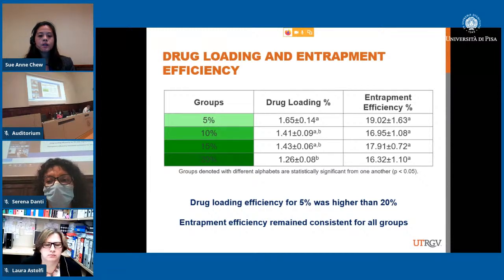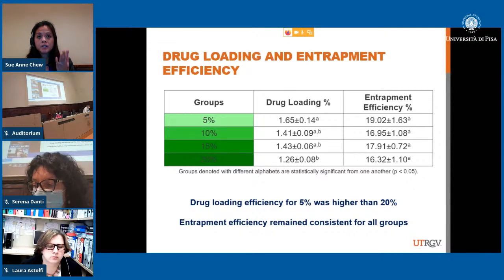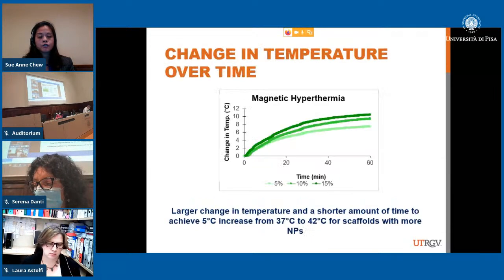So, we wanted to characterize them with drug loading and entrapment efficiency. We were able to make sure that the scaffolds were generated evenly and repeatably, where their entrapment efficiency remained consistent for all groups. But as expected, if we put more nanoparticles into the scaffolds, the drug loading percent goes down because the iron oxide nanoparticle concentration goes up. We had to adjust for the minocycline that is actually injected with the scaffold.